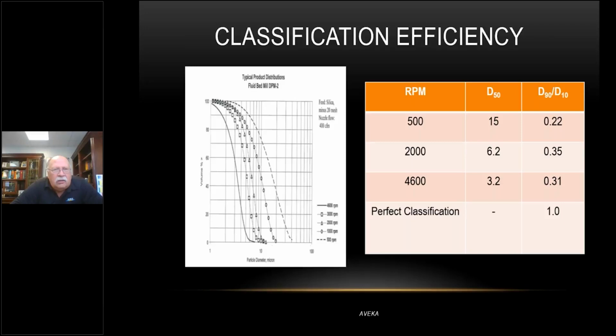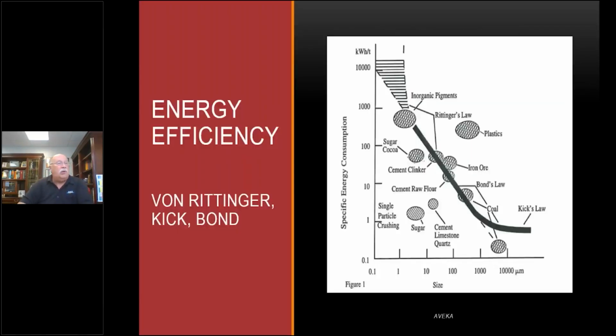Here's an example of a jet milling followed by classification that we did on silica. What you can see is that depending on the rotor speed of the classifier, and we'll talk about this in just a second, you can move to different size particles from one size down to the other by changing that rotational speed. The efficiency is defined as D90 over D10, or D10 over D90 actually. The closer that number is to 1, the tighter the distribution, the sharper this peak is in this particle size here. If you have perfect classification where everything is either above or below a number, you have a D10 over D90 of 1. We'll never see that. You can see these numbers of 0.3, 0.2. This is not a great classification, but for this particular product, this is what we actually got.